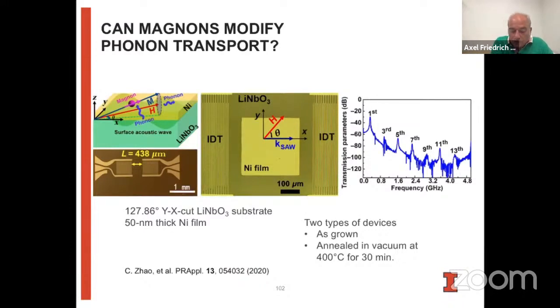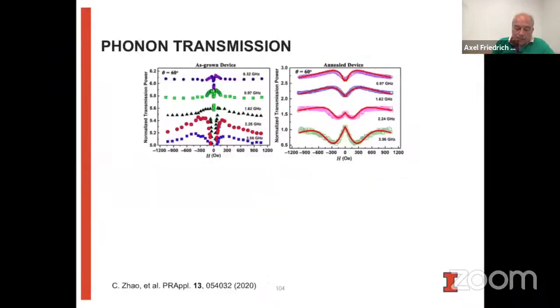That's very good. Certainly, what we looked at is just how different annealing conditions change the coupling between the two. We didn't see that much difference from substrate to substrate. So I don't think we have much systematic work where we can say how things change as the quality of the surface acoustic wave propagation changes. But all I can say is that it does become a very complicated kind of story. This is essentially what you see here, right? You can actually get even an enhanced transmission of the phonons because of the coupling to the magnons if the coupling is significantly weak.